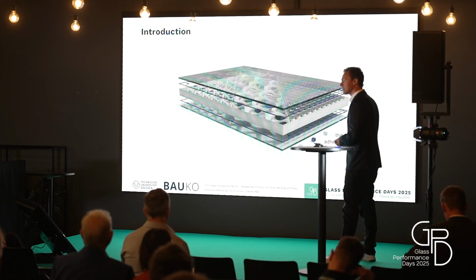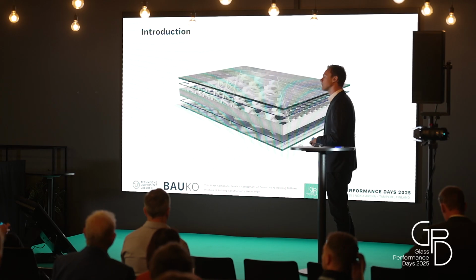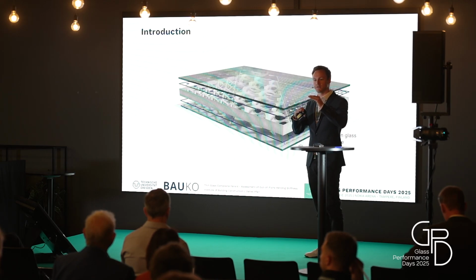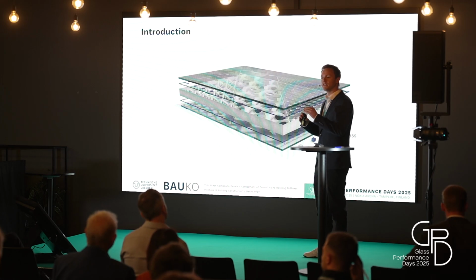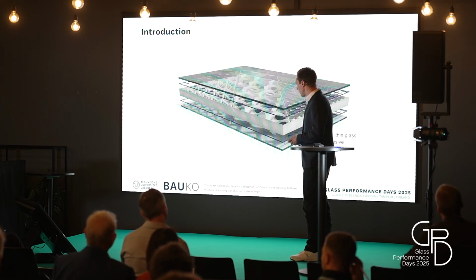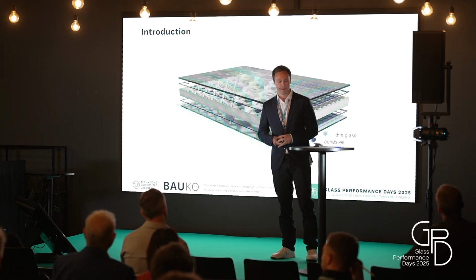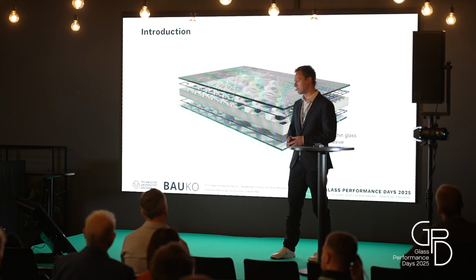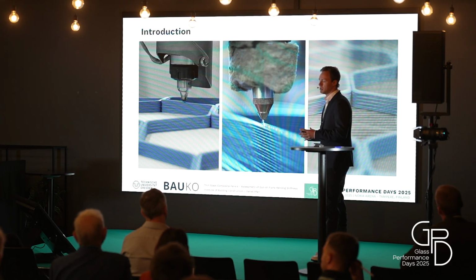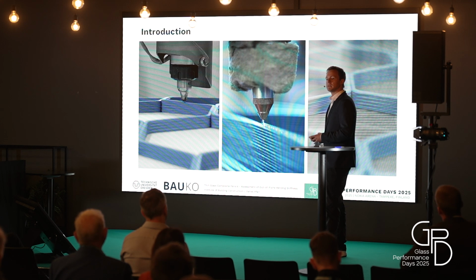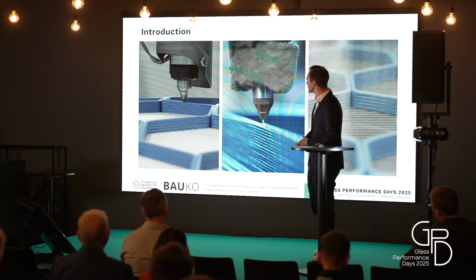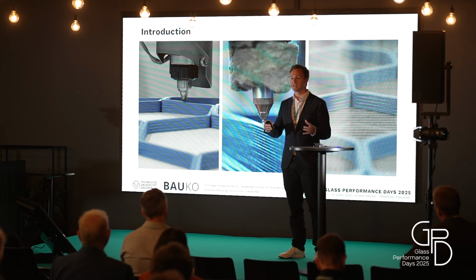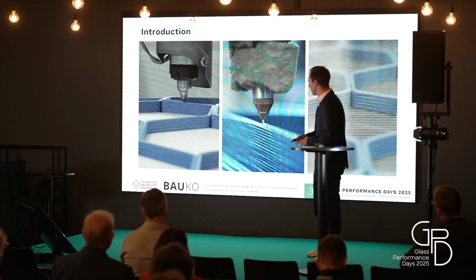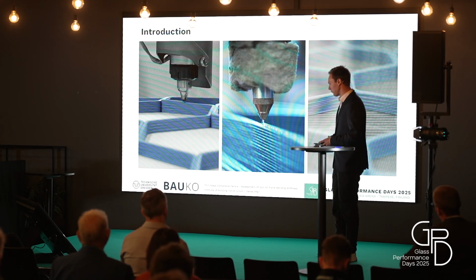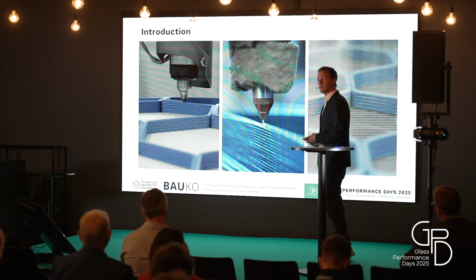So let's get started with this rendering. It shows the thin glass composite panel, or the concept of the thin glass composite panel. So we take two very thin sheets of glass and we adhesively bond them to some kind of core structure. In our case, it is a 3D printed, additively manufactured core structure made of a thermoplastic polymer. How is that made? We set up a whole manufacturing process. After a design phase, we can come to the production in our laboratory, and on the left-hand side you can see the additive manufacturing. In that case, we are using a quite simple honeycomb structure, but that is already very sufficient from a mechanical perspective.